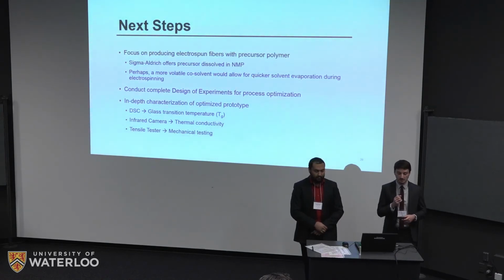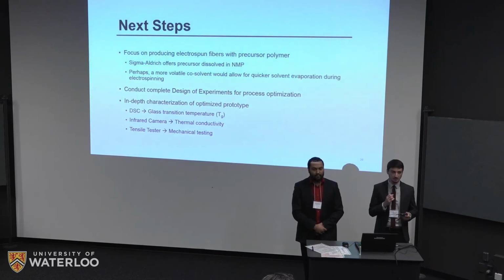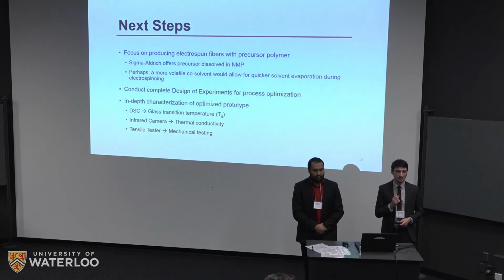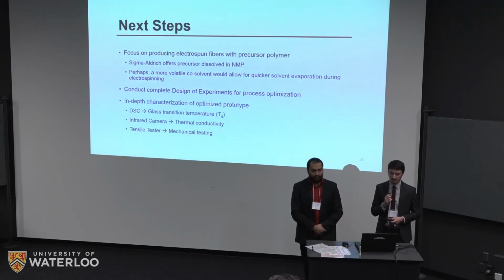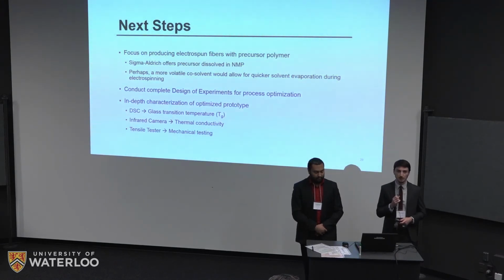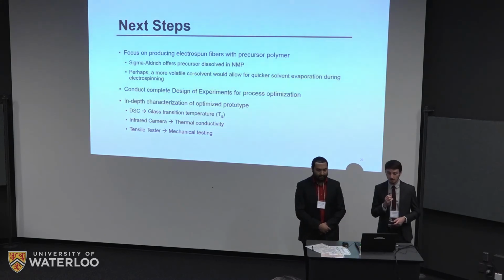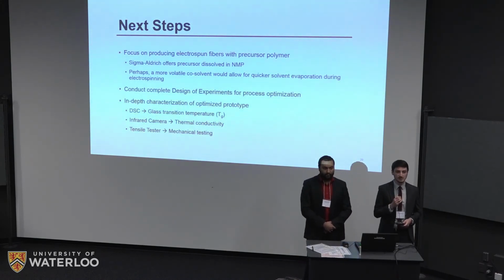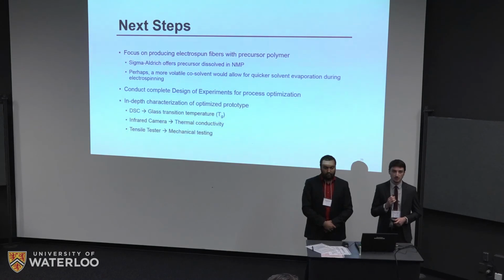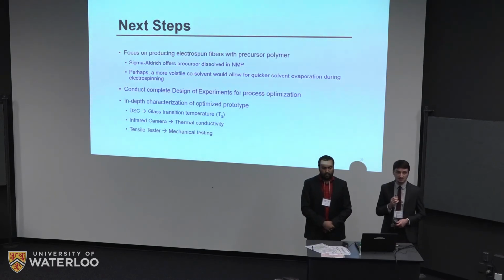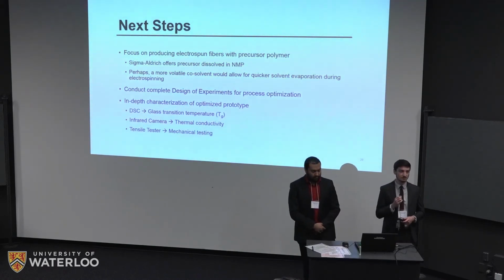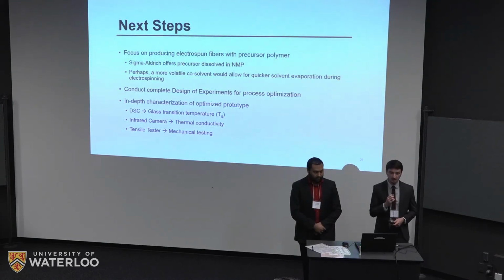The issue with that is even though we were able to obtain some of this supplier material, it was dissolved in a much less volatile solvent than what we were using. It was dissolved in NMP, which was not evaporating properly in our electrospinning setup, and therefore was not forming fibers. It was much worse than actually what we were using when we made our own. So we would have to find a way to get around this. Some ideas would have been to maybe use a co-solvent that would evaporate faster so that we'd be able to get better drying and so we could form cohesive fibers.